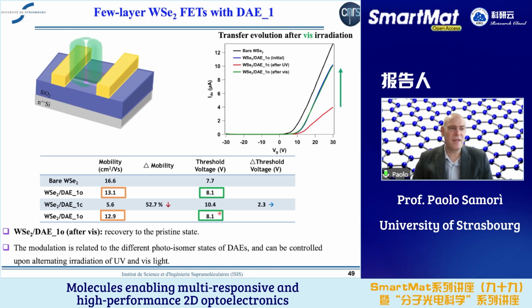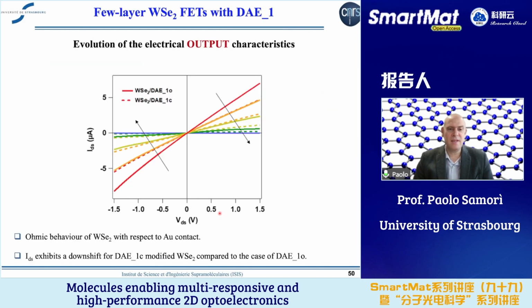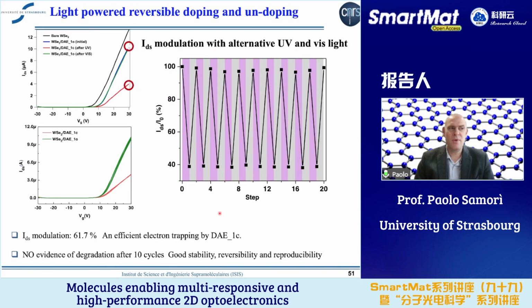So by modulating the state of the diarylethene, we can control the current through the tungsten diselenide. Now, if you look at the output characteristics, they show an ohmic behavior, and this indicates that we have a good contact with respect to the gold electrodes. And actually, we can make cycles by illumination with UV and visible light, one after the other, and we can